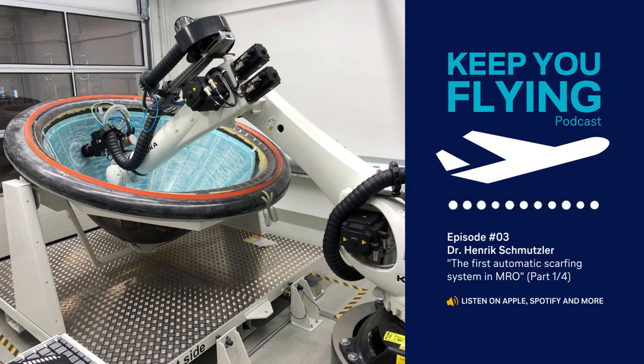Moreover, the position of the parts often led to less ergonomic working positions, where maintenance crews had to work in overhead or kneeling positions for a long period of time. The removal of hundreds of rivets and bolts was also exhausting, especially for shoulder and arm joints. Now our maintenance personnel can conveniently conduct all these operations from a control desk, without the risk of being exposed to hazards such as noise, dangerous substances, and difficult working conditions. When it comes to the nose radome repair process, our system even allows crews to perform operations that were not economically feasible during manual processes. In many cases, the outer skin of the radome sandwich material is not damaged and does not have to be removed. The robot makes it possible to only remove the inner skin and honeycomb material without damaging the outer skin in areas up to two to three square meters, significantly reducing the needed prepreg material for the repair by up to 50%.